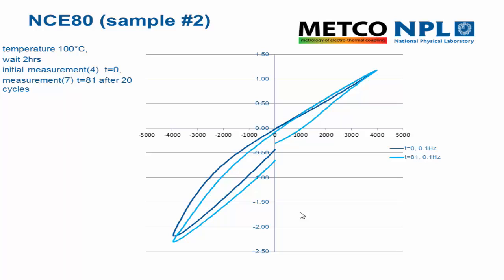So these measurements taken by aixACCT were at 100 degrees C, waiting for 2 hours at that temperature, and then doing a number of measurement cycles before taking the final measurement. And you can see that having done that, we get much, much closer agreement. So the measurement cycle, the measurement time, the time spent at temperature affects these measurement results.